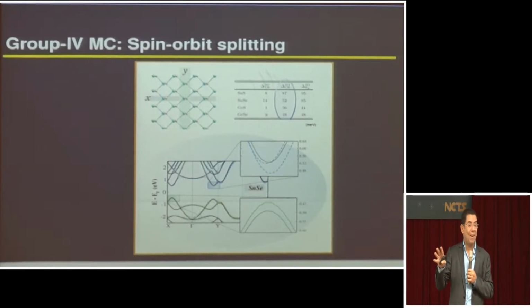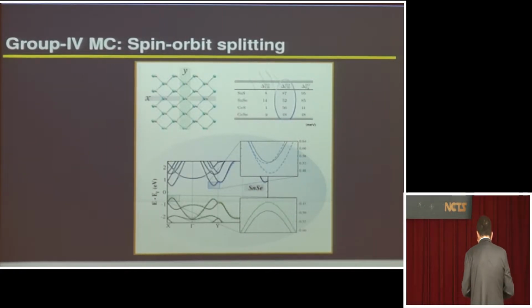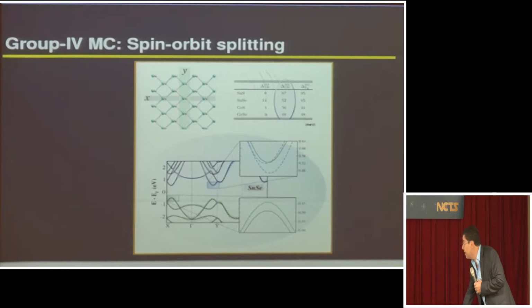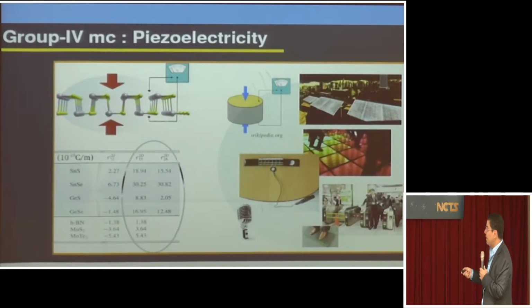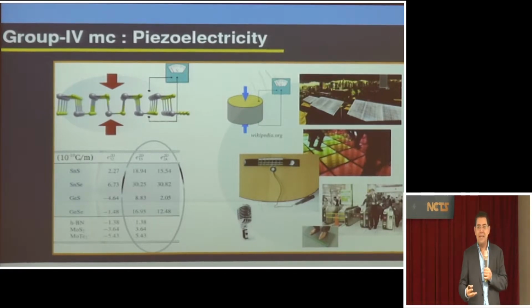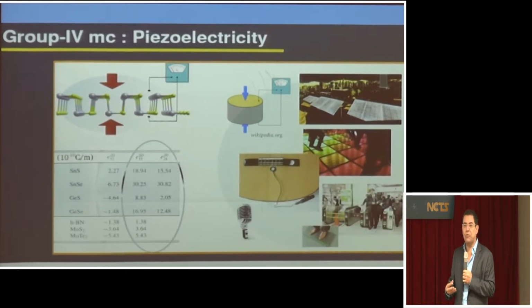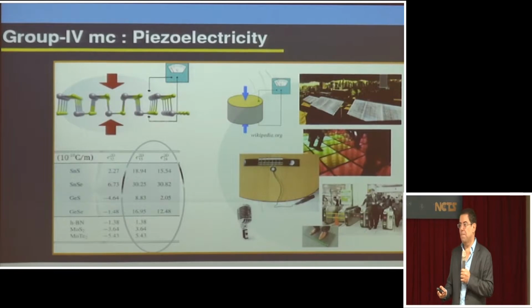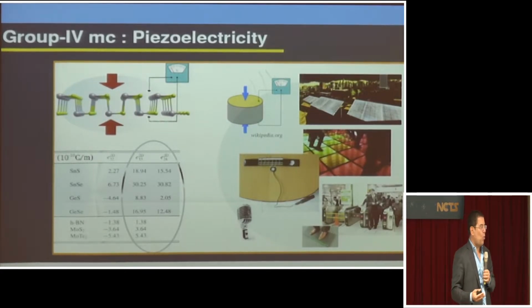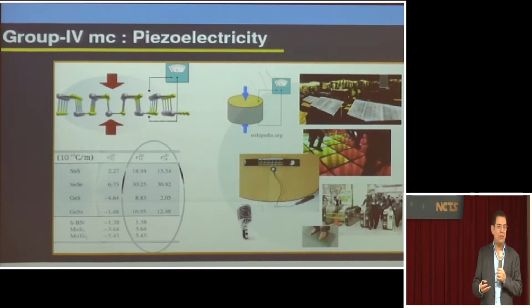Okay, so that's one of the characteristics of the band structure of this material. So this has very interesting consequences. I'm going to talk more about this in a little while. Another thing: because of the very low symmetry, this material doesn't have inversion symmetry, so these crystals show piezoelectricity. Okay? If you compress these materials, if you apply uniaxial pressure, you actually get electric charge out of them.